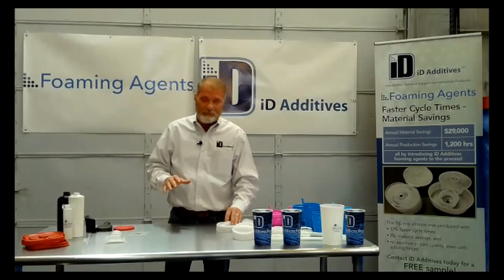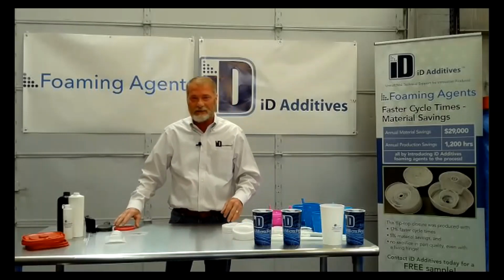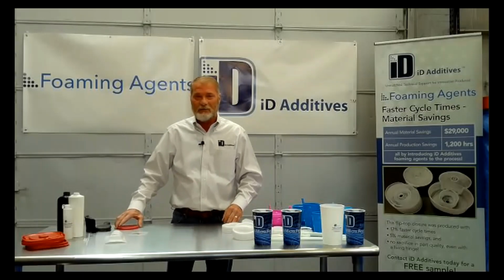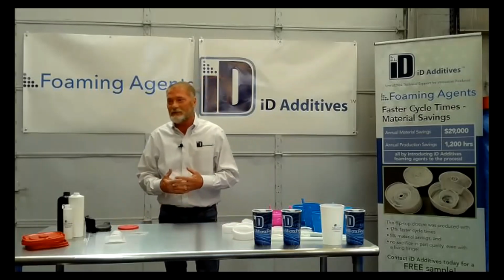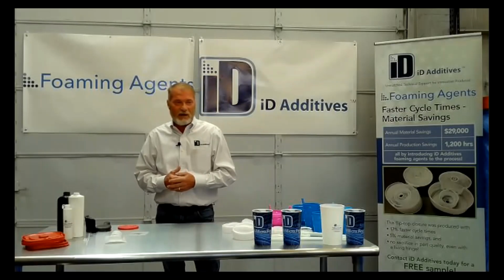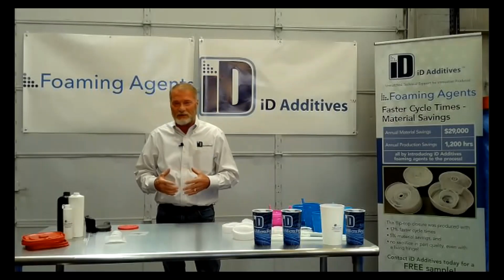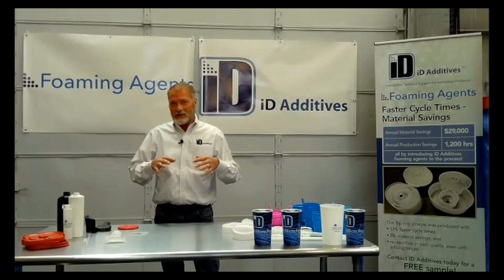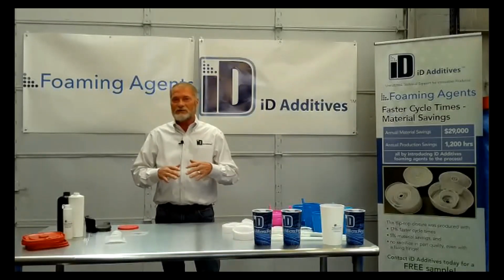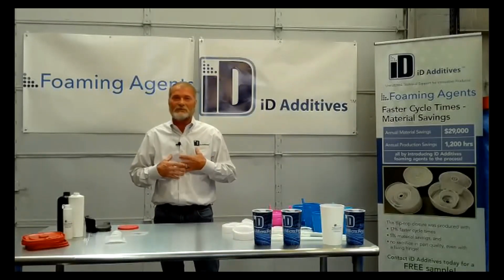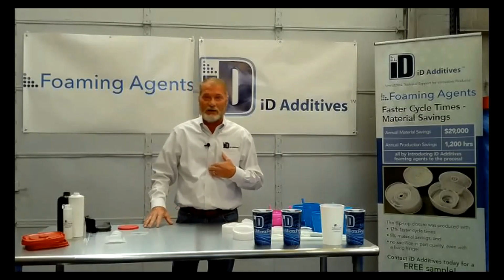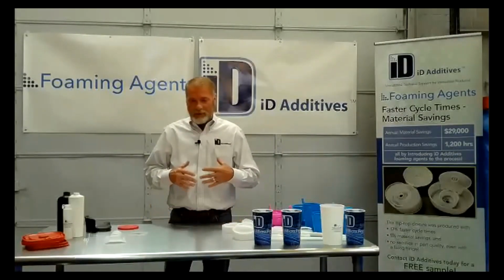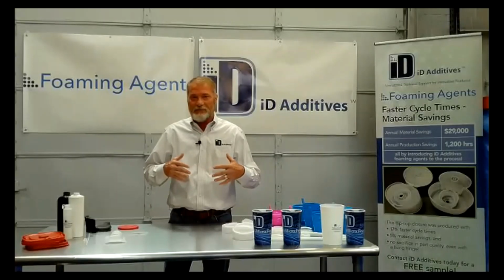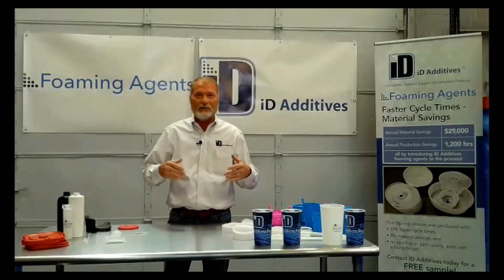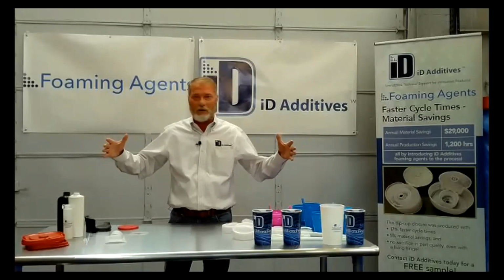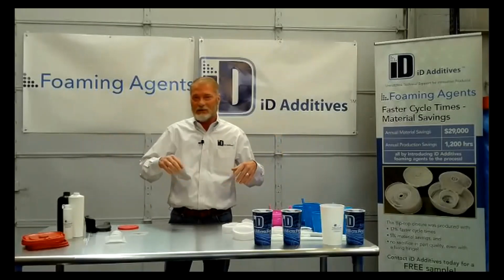So speed is important, even if it's non-aesthetic. The faster you get it in, the better it is. Unless you've got, you know, I've foamed parts that they want the splay look. They do want a density reduction. They do want cycle, which foaming agent, as far as I'm concerned, endothermics, I always get cycle and weight. But they want that look, but the faster you inject it, like in a bin or a large structural foam part, you jack it in fast, you'll get swirls.